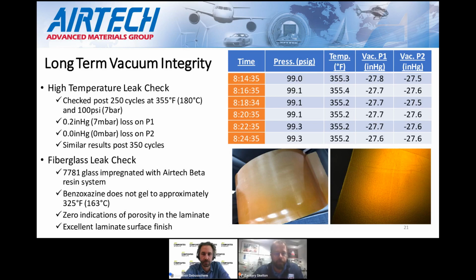But we also performed a fiberglass leak check. For folks that aren't familiar with it, it's kind of the gold standard in tooling for knowing where a leak is. So that 0.2 inches of mercury that dropped, that 7 millibar, if that was in the tool face, that would be problematic. But you have all these potential sources like bagging ears, through bag connections, couplings to hoses, couplings to the autoclave. All of those can leak a little bit. So, understanding that the tool surface is solid.